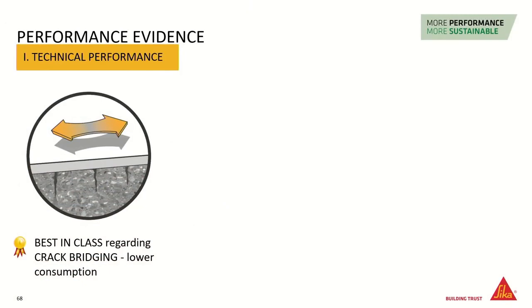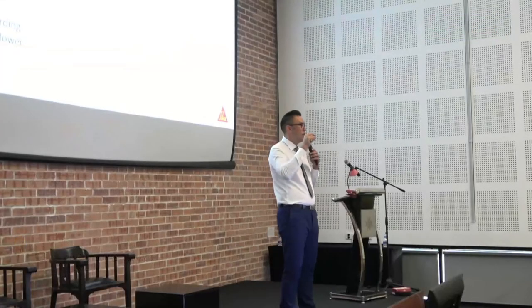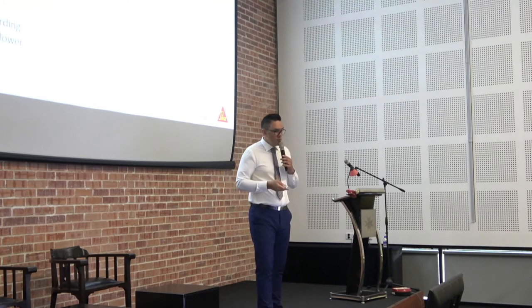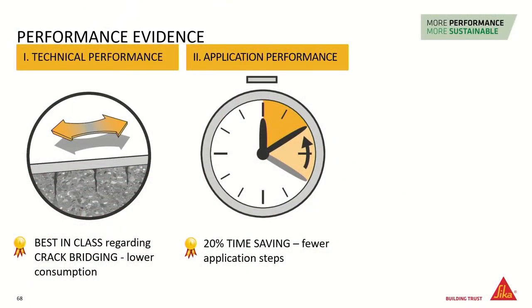And then we have to have performance evidence. So we test in-house and then we pass it out to external for validation. So we get best in class regarding crack bridging with a lower consumption. Normally for a high crack bridging coating, you have to have quite a thick dry film thickness, usually around minimum 340 micron or something like that. But we can reduce the amount that you need and still have the same crack bridging performance. So it means that you can use less material. Because you use less material, you save time as well. So the client gets the benefit of the time saving, the contractor gets the benefit of the time saving, and less material.